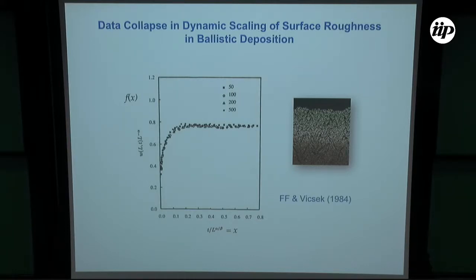Well, just for historical reasons, like David was showing from 92 years ago, this almost feels like 92 years ago, but this is the original simulation in our paper from 1984. This is the largest system size we could do in one dimension, basically 1 + 1 dimension simulation of ballistic deposition, in which I'm plotting the scaling function. So this is W times L to the minus alpha. The values of alpha and beta don't matter really. Don't worry about those. But you can see that the data did show a very nice collapse with two different values of the exponent, validating the fact that you really in thin film growth have two length scales.